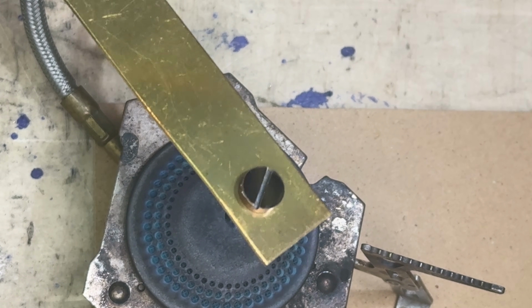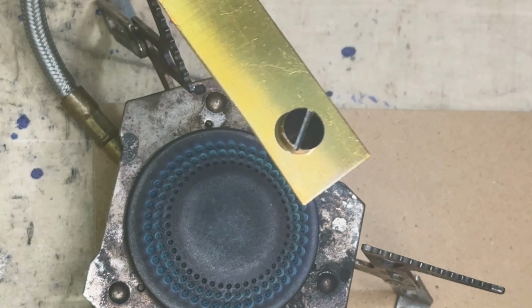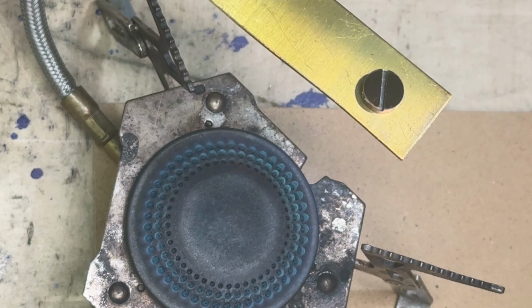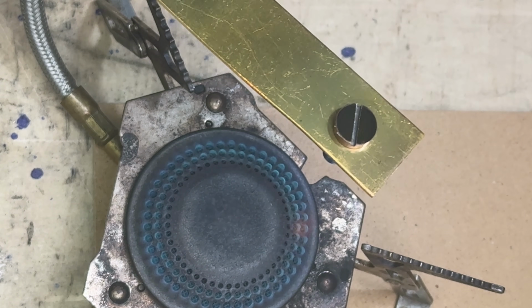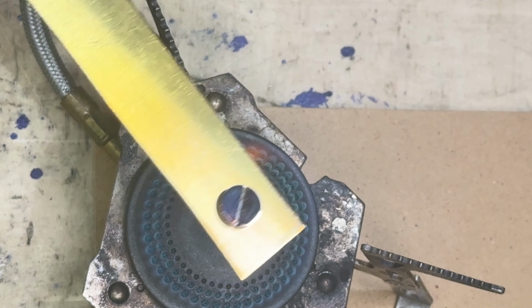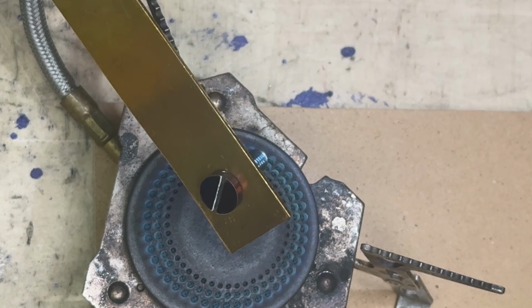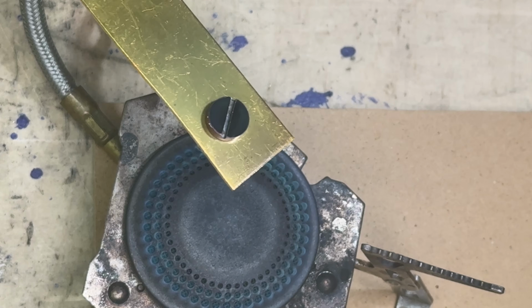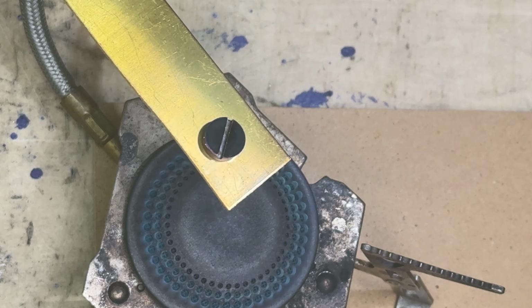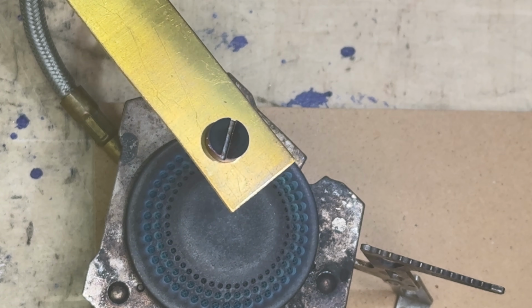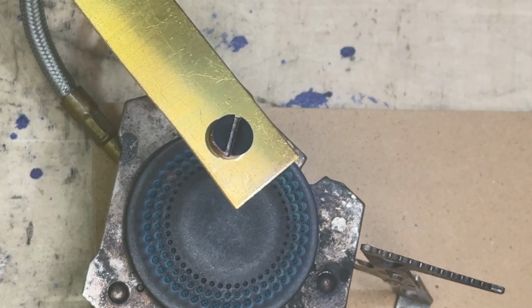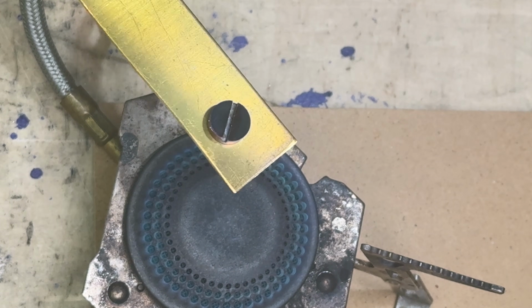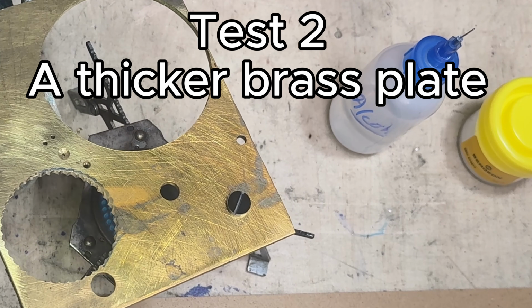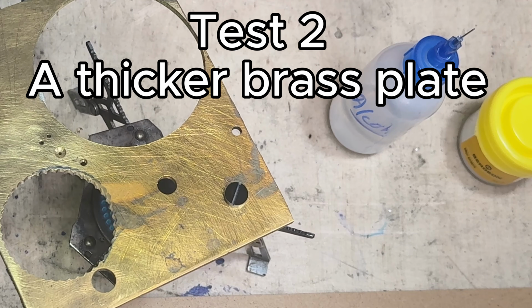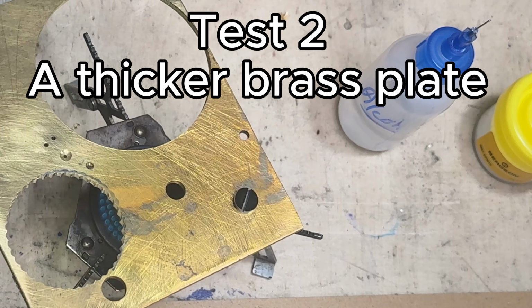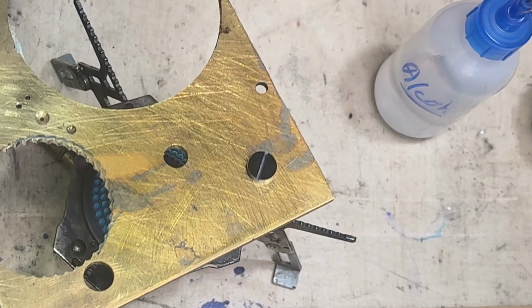So you can see here that the threaded section of the screw is good and blue, but the sides of the screw head are still purple. So I think the heat transfer through the thin brass is not really good enough. Although the top of the screw seems to be going blue, it's not terribly even. So I think for my next test I will try a thicker piece of brass. Alright, it's rapidly going blue now, but more on one side than the other, which is a bit disappointing.